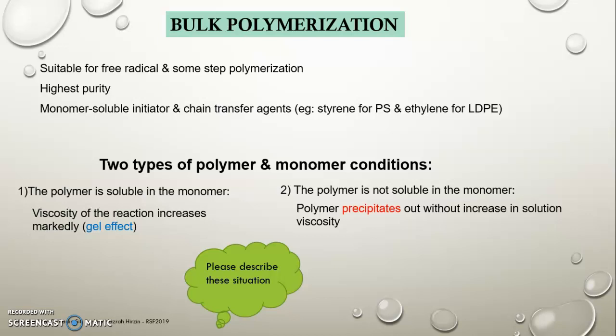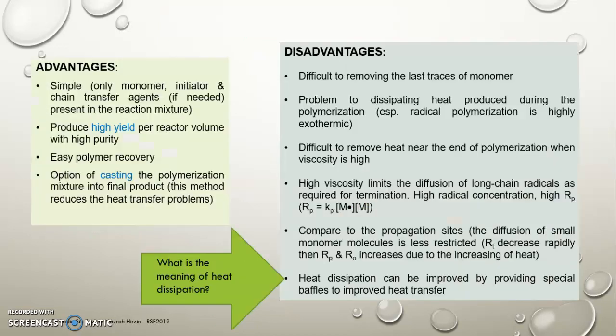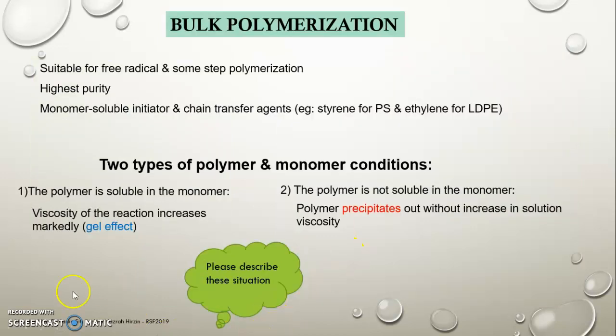There are two types of polymer and monomer condition for bulk polymerization: first, the polymer is soluble in the monomer, and second, the polymer is not soluble in the monomer. Polymer soluble in monomer means that the viscosity of the reaction increases, which will give the gel effect. So we will look at what the gel effect is. And polymer not soluble in the monomer means that the polymer will precipitate without an increase in solution viscosity. This situation is not the situation for the gel effect.